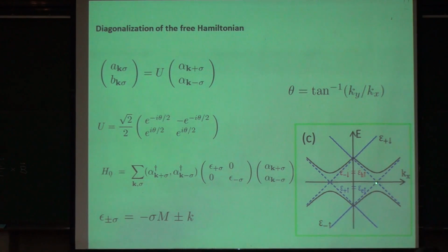After the calculation, let me tell you the basic result. Without this Coulomb interaction, electron-electron interactions, the band structure of the ferromagnetic graphene is just these blue curves. There's a separation of the Dirac points, then it's a linear dispersion. The important thing is that there's a crossing here and here. And at this crossing point, the energy is degenerate, right?